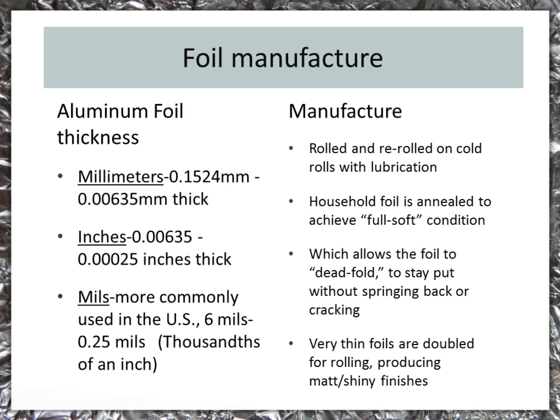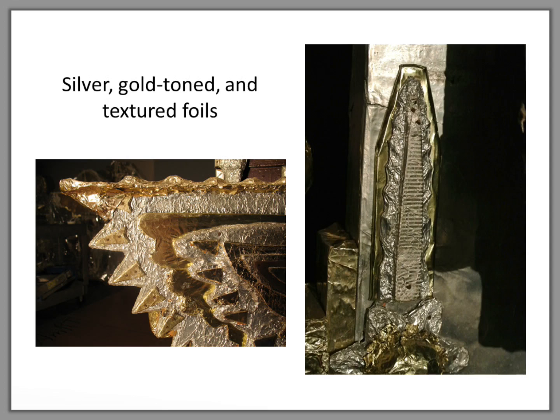The foil may be laminated to a carrier or backing sheet with all kinds of adhesives. The actual paper and foil laminating adhesives for Hampton's foils are unknown, but one paper backing did test positive for polyvinyl acetate resin, possibly originally intended for heat sealing applications. Foils used in the fabrication of the Hampton Throne appear to be of 4 general types: out-of-the-box Reynolds household foil, used and new, textured foils, which were mainly silver-colored, as seen in the image on the right, silver foil and paper laminates, and paper laminated foils with gold-toned coatings.